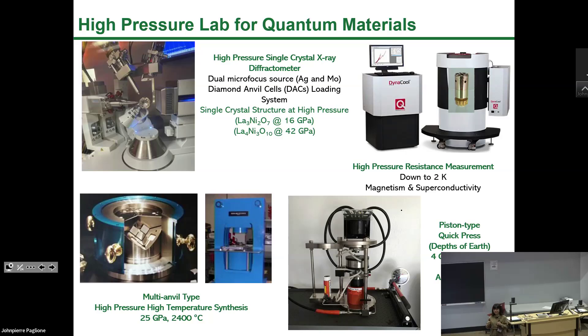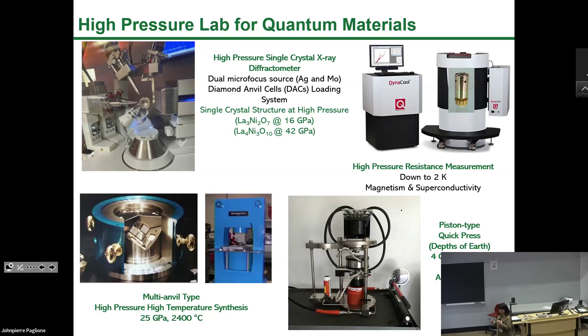We have complete DAC loading systems in the lab so students can do other experiments. We recently did studies with Dr. John Mitchell at Argonne National Lab working on nickelates, measuring La3Ni2O7 up to 16 GPa, and for La4Ni3O10 we tried a new cell to go to 42 GPa. As a chemist, we want to know the crystal structure exactly — we care about chemical bondings and atomic occupancy. After getting crystal structure information we do high pressure resistivity studies.